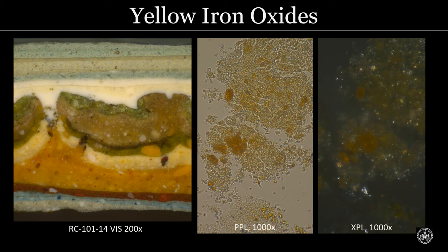So analysis of these bright yellow particles detected mostly iron and oxygen. And then in these images on the right, we see a dispersion from that deep yellow paint. And we have a mixture of lead white and yellow ochre. And like I said, I also found some red lead as well, but you don't necessarily see that in these images. But I just really love these really enormous yellow iron oxide particles in this cross section. And I took dozens and dozens of cross sections from this area in the house. It was from the stair passage, and they all had these really wonderful coarse, bright yellow iron oxide pigments.